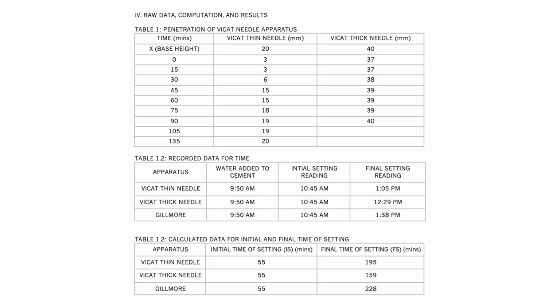Based on the results of using multiple testing methods, including the Gilmore apparatus and Vicat needle, all of the samples had set at different times. The ASTM C191 and C266 standards stipulate that the Vicat needle test requires a cement to undergo an initial setting time ranging from 49 to 202 minutes, followed by a final setting time ranging from 185 to 312 minutes. Both the thick and the thin specimens tested by Vicat needle apparatus met the criteria for an initial setting time of 55 minutes. However, only the Vicat thin needle met the standard for final setting of 195 minutes, while the thick needle test did not.